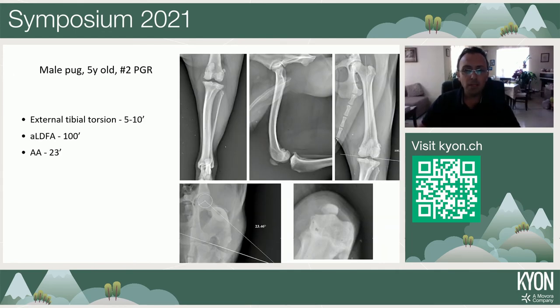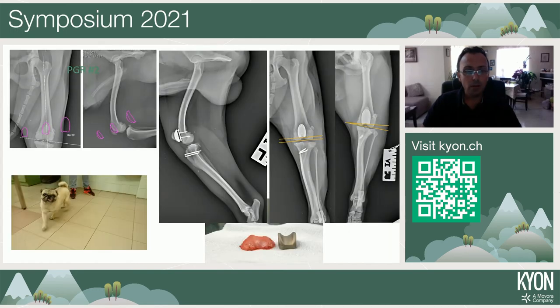This is one of these cases, a male pug, 5 years old. In this case, we identified a little bit less than 10 degrees of external tibial torsion. There was a very wide distal femoral varus, about 100 degrees of anatomical lateral distal femoral angle, and the angle of anteversion was 23 degrees. So in this case, we used a tibial tuberosity transposition to correct the external tibial torsion, in combination with a patella groove replacement size 2 implant.